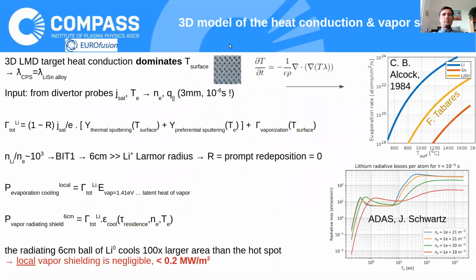So we built a three-dimensional model of heat conduction and vapor shielding. Unfortunately, the heat conduction dominates the surface temperature, which means that the vapor shielding was pretty weak in our experiment. The heat conduction equation is pretty simple. We had to assume that the heat conductivity in the capillary pore structure is equal to the lithium-tin conductivity, because it's perpendicular to the surface.